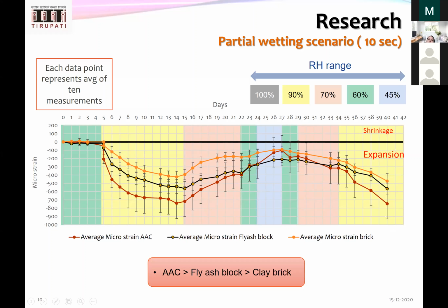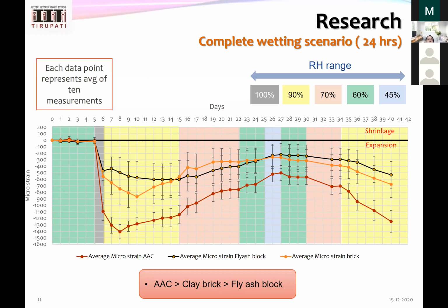Then we did a complete wetting scenario. That means we are keeping this brick for 24 hours in water. What happened here is your strain level has tremendously increased. Obviously, a lot of water has been absorbed in the brick. So if I start measuring the expansions, a lot of expansion has happened in it. It has come to around 1400 microstrain. And it is very high in the AAC block.